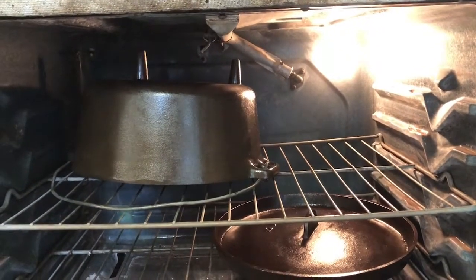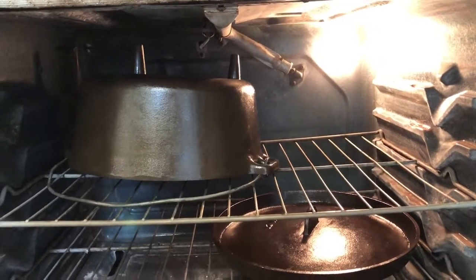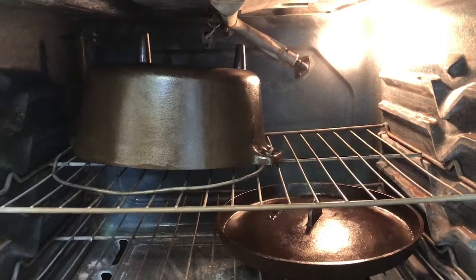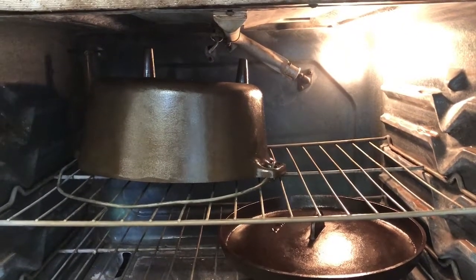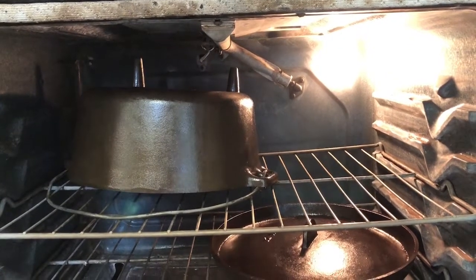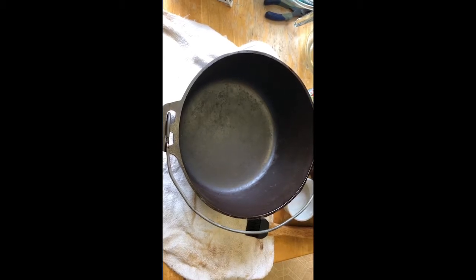It's going into the oven now for an hour at 400 degrees, and that's going to take that oil and bake it into a polymer on the pores of the cast iron. The whole reason we season an oven is, number one, to protect the cast iron, but number two, it also makes this pretty much nonstick cookware as long as we maintain that seasoning. Into the oven, upside down — both cooking surfaces facing down so we don't get any pooling of oil and get the seasoning too thick in any places. The outside should just run off if it's going to run anywhere. It's going into the oven at 400 degrees for about an hour. When it comes out, it will be nice and black.